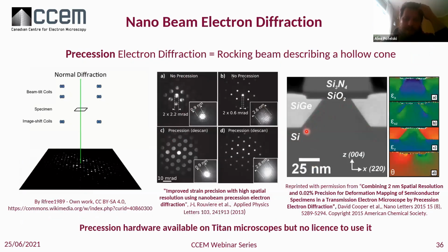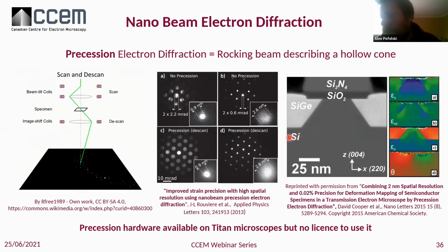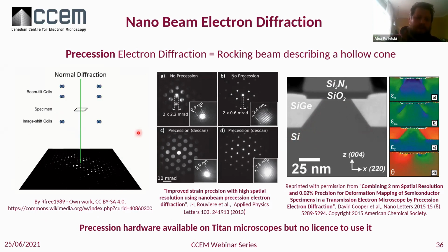One word before I finish on the diffraction technique is the use of precession, because especially in the strain context, it has been showing some great results. The idea of precession is to rock the beam by describing a hollow cone shape. On the left you have an animation of that. Here you have a normal diffraction, where you just collect the diffraction on your CCD. Now you can tilt the beam in a certain manner, and use a descan to compensate this tilt, and then make your beam describe this circle, so that it will describe this hollow cone.